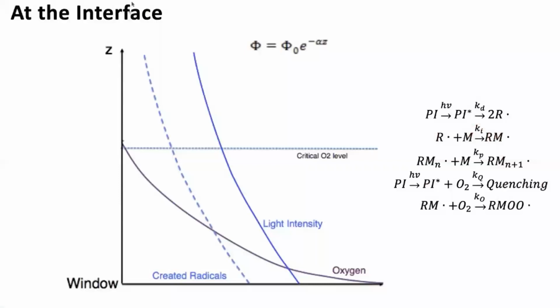This is a generic concentration axis shown here, and we're going from the surface of the window up into the reservoir. And what you can see here, as light enters the reservoir from underneath, the intensity of light is the highest right at the interface with the window, and then it tails off as you go into the resin just due to molar absorptivity.